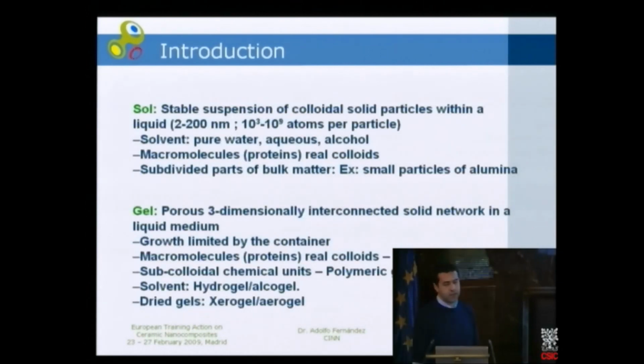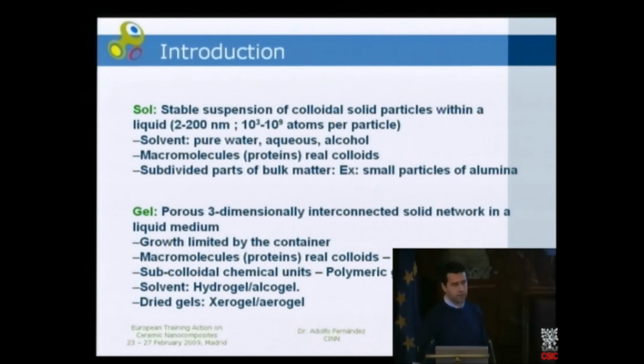I will start with general definitions. For example, when we talk about Sol, this is defined as a stable suspension of colloidal solid particles within a liquid. These particles must be small enough to make the repulsion forces stronger than the attractive ones in order to maintain a stable suspension. And these particles will be formed by between 1,000 and 1,000 million atoms per particle. If not, we are talking about molecules in solutions.